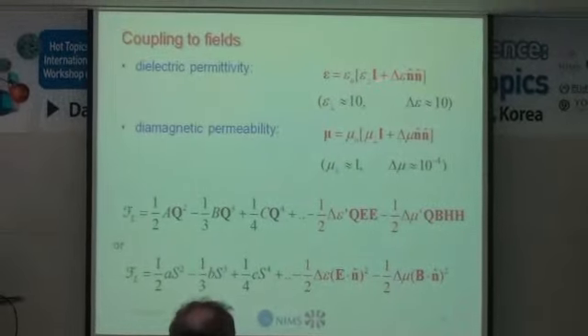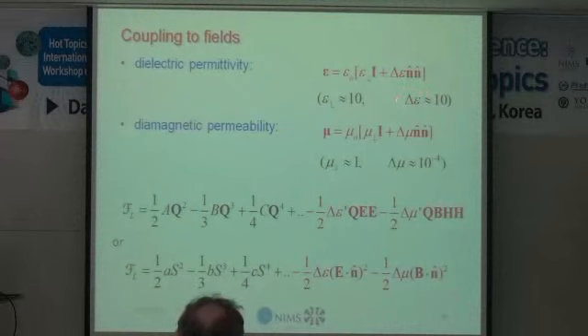Now, interestingly, the anisotropy in these materials is pretty big. So the anisotropy, the difference in the two principal values, is just as big as one of them. So that's an important aspect in the electrical case. In the magnetic case, the anisotropy is really small. So although these materials respond to magnetic fields, the response is not so strong as in the electric case. And then one can put this additional field contribution into the free energy, both in the electric and the magnetic case, and either in terms of Q or in terms of the scalar order parameter and the director, and the terms look like that.